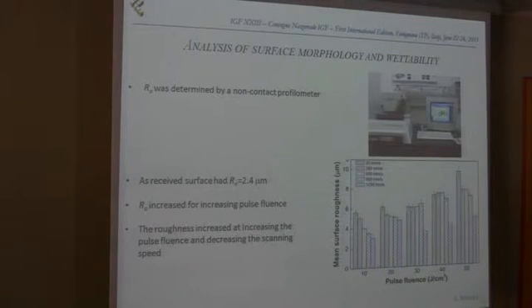And these results were also confirmed by the surface roughness measurement that we performed with a non-contact profilometer. We measured basically the mean surface roughness. The baseline, so the as received, was around 2.4 microns. And as you can see, once again, the more we reduce the scanning speed, the more we increase the roughness.